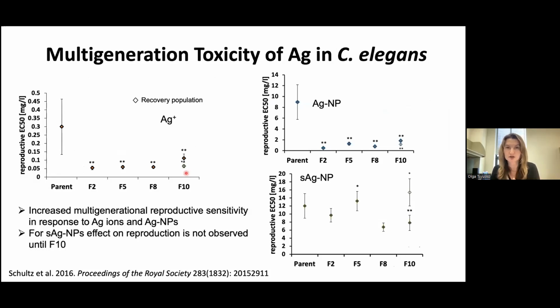If we look at multi-generational toxicity of pristine silver ions and sulfidized silver nanoparticles over 10 generations, just to walk you through what we see here: it is the concentration that is causing a 50% decrease in reproduction. You can see as soon as the second generation, that concentration is dropping significantly and consistently persisting up to F10, meaning that you need a much smaller concentration to cause a 50% decrease in reproduction. Exactly the same pattern is observed in response to pristine nanoparticles. And in response to sulfidized, we don't see these effects until we reach generation F10.